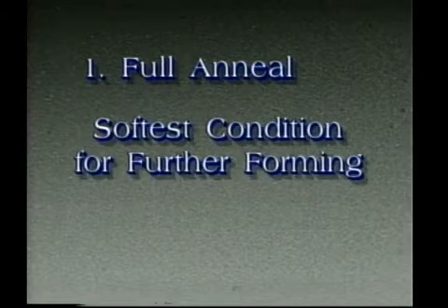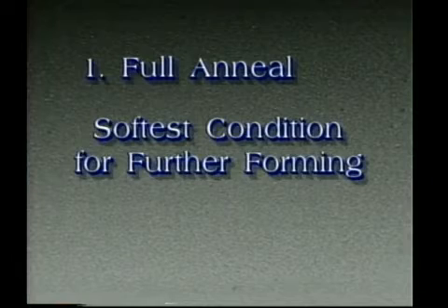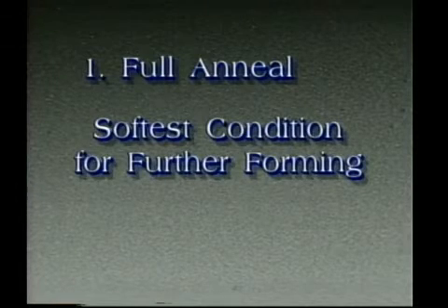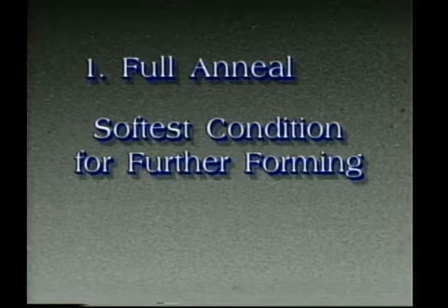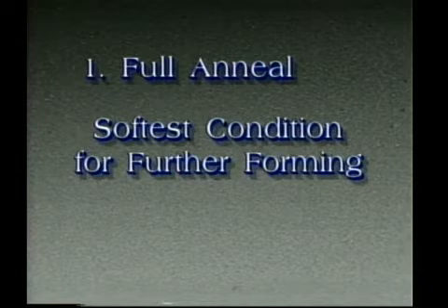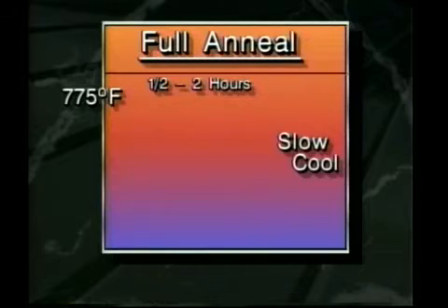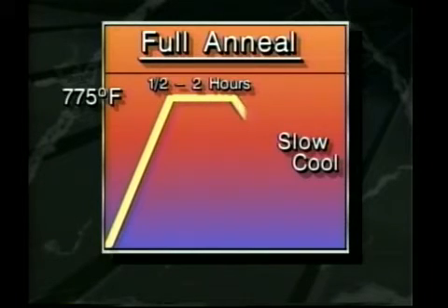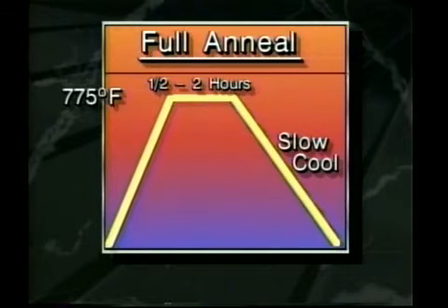Full annealing is used to obtain the softest possible condition to allow for further forming operations. Full annealing eliminates all prior conditions. It is often used to homogenize cast structures. Full annealing aluminum alloys is accomplished by heating the material to 775 degrees, holding for 1/2 to 2 hours, and then furnace cooling slowly, typically at 25 degrees per hour, down to room temperature. The 775 degrees is high enough to dissolve some of the hardening elements into solution.